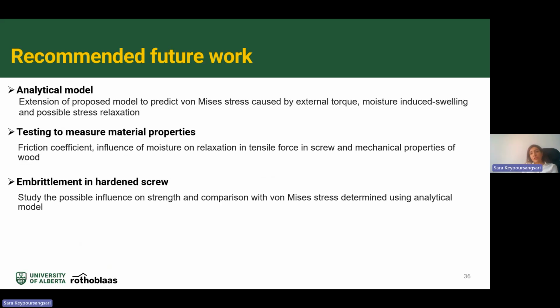For future work regarding the analytical model, it is recommended to extend the current analytical model to predict von Mises stress due to the external torque and moisture-induced swelling and the potential stress relaxation, because there wasn't much data about the stress relaxation, and we considered some assumptions. More research is needed in these areas, and also regarding the material properties.